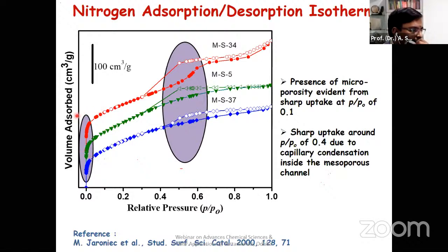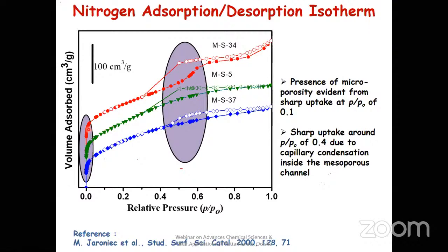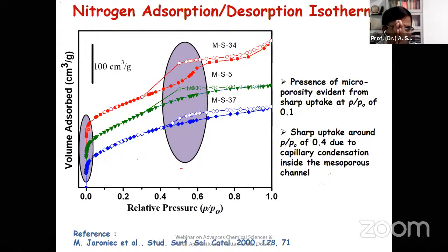When you look at this, at P by P0 below 0.1, there is a sharp uptake of nitrogen. What does it mean? You have very, very narrow channels. When you have narrow channels, only one monolayer of nitrogen is going to adsorb. So whenever there are small narrow channels, with monolayer adsorption, the condensation of nitrogen occurs at P by P0 below 0.1, which supports that this is a microporous nature.